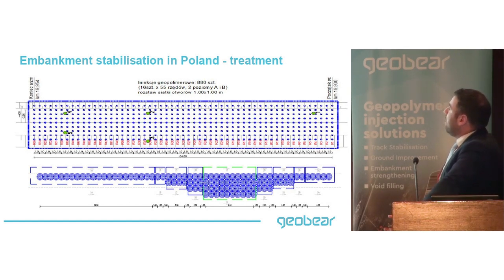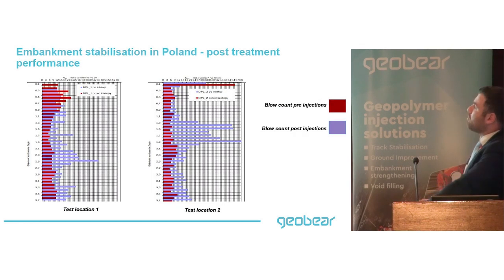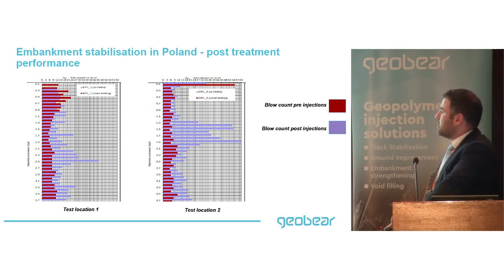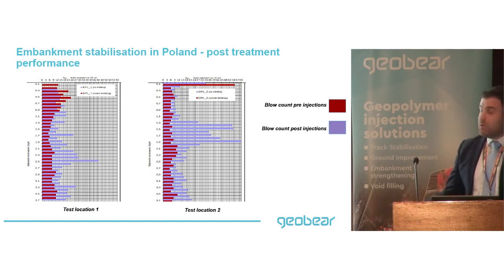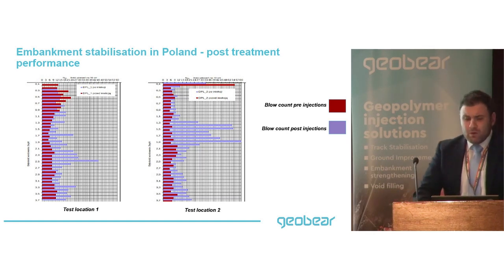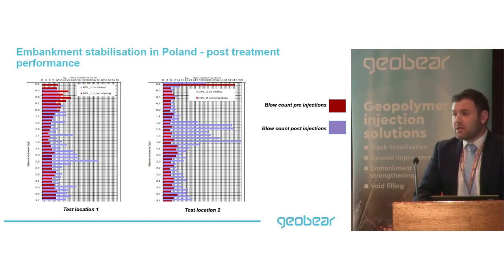We injected almost 880 injections, quite a lot to be honest, and the client carried out dynamic probing before and after in two different locations. The red bars represent the number of blow counts before the injections, and the blue bars represent the number of blow counts after, in location 1 and location 2. You can see a substantial increase in blow counts before and after - in some instances almost up to 6 times. But overall there's a great improvement within the treatment area. As far as I know from the client, the problems have basically stopped, and we managed to stabilize the issue.